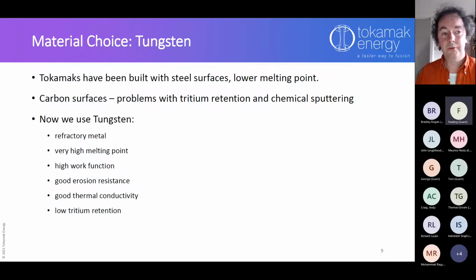Thought I'd say a bit about the materials. We've actually ended up choosing tungsten or possibly molybdenum, a refractory metal. Tokamaks in the past have been built with steel surfaces. There's Inconel and there's a material called Eurofer, which has been developed from tokamaks, which has lower activated components in it, but also carbon surfaces. So in JET, the Joint European Torus at Culham, which held the record in 1997 for the most fusion energy produced, it had all graphite surfaces, because graphite is very heat resistant. Unfortunately, they found that they have problems with tritium retention and a thing called chemical sputtering, which is another type of sputtering that erodes those surfaces away really fast.